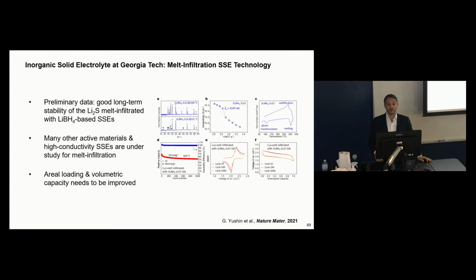And so even though lithium sulfide, in principle, has much higher volume changes, if you assemble it in a fully expanded state, it doesn't have to expand anymore. And in fact, we could achieve very good cycle stability for the lithium sulfide and the same technology, melt-infiltrated electrolyte technology.